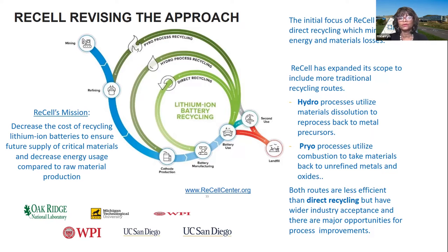RECELL has expanded to hydroprocessing. With hydroprocessing, basically you're using acids to dissolve the materials, and what's produced is leached out as metal precursors. And then with pyro, intensive heat is applied to the battery to burn off the organics, and what you're left with is the slag that is then separated using the hydro processes.